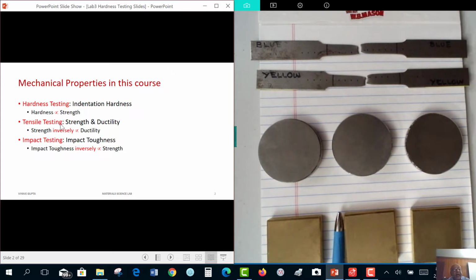Then we did tensile testing in lab number 2, where we focused on strength and ductility, and we found that strength varied inversely with ductility. So if we did something like in our aluminum specimens, precipitation hardening or precipitation strengthening, we reduce the ductility. If we increase the strength, we reduce ductility. That is what you also saw in your lab 2 steel specimens. The T4 specimen, which was skin rolled, had lower strength, higher ductility. And if we had cold rolled it to quarter hard, increasing its strength by almost 50%, we decrease the ductility.